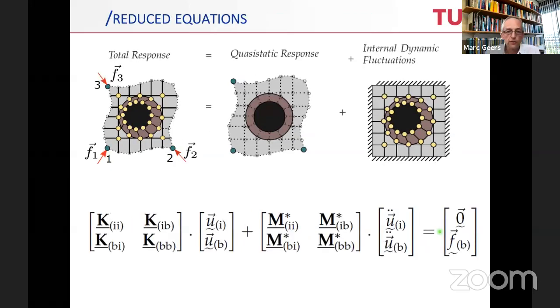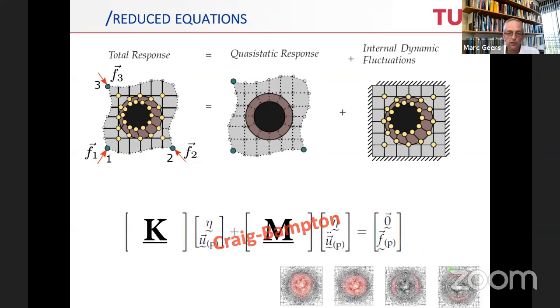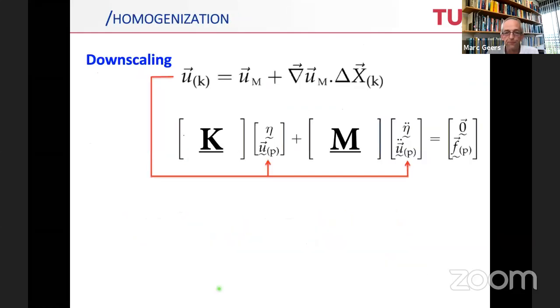We go back to the original discretized system of equations, which is shown here, and we apply the Craig-Bampton decomposition on this system. You actually apply a change of variables, which means that the same system of equations is now recast in this format. And the degrees of freedom that are left are actually the amplitudes of the internal vibrations and the prescribed degrees of freedom. So there's an enormous model reduction included in setting up this problem. In the little movies at the bottom, if you manage to see them, you again see the typical eigenmodes that are relevant for this problem.